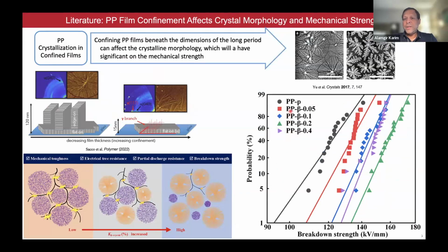As you can see, people have taken polypropylene with different nucleating agents, adding more and more nucleating agents. You can increase the beta phase, and clearly you can go from black to the green, with increasing beta phase volume fraction. So there is some precedent that controlling not just the crystallinity, but the type of phase can help you boost the energy density. These are bulk films.